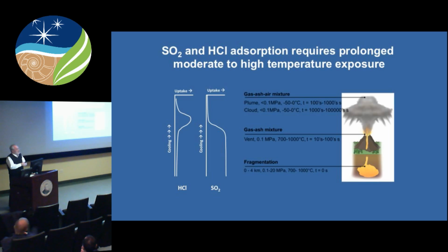But we, being petrologists and volcanologists, decided let's look at the birth of the ash. What's the first thing that the ash sees when it's born? And the first thing that it sees is this ugly cocktail of volcanic gases which were, a moment before, contained in its bubbles and in some sort of disequilibrium, but not wholly unrelated to the rock around them. But once they are released and that PT path towards this dusty gas going to the surface starts to really kick in, they are horribly out of equilibrium. Their speciation starts to cascade down to what it will be at low temperatures, and they start to attack the surfaces of the volcanic ash within seconds of the eruption coming out.